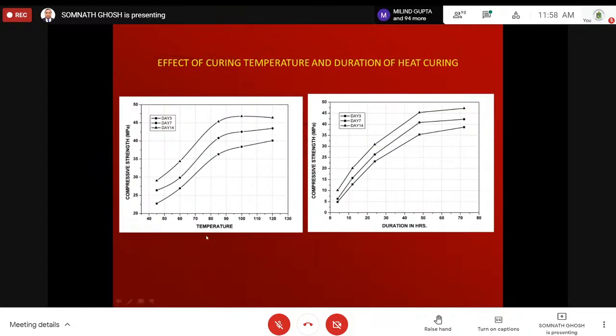Then you see this is the curing temperature, from 40 degrees to 120 degrees. We have varied it. We found that around 85 is best. Beyond that, even if you go for a higher curing temperature, it will not really give you a better result. Slightly better. That's why we fixed it at 85 degrees. There are many other aspects also. Hours of curing: 10 hours, 20 hours, 30 hours, 40 hours, up to 80 hours we did. And we found that around 50 is good. Beyond that, we are not getting a lot of advantage, because if the duration is more, your energy consumption will be more, and cost will be more.